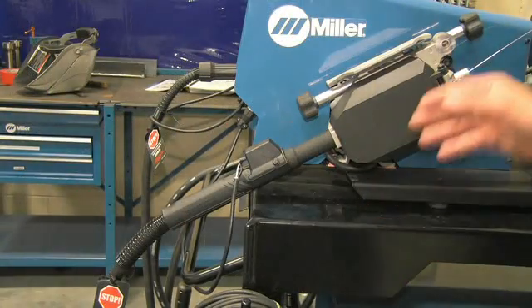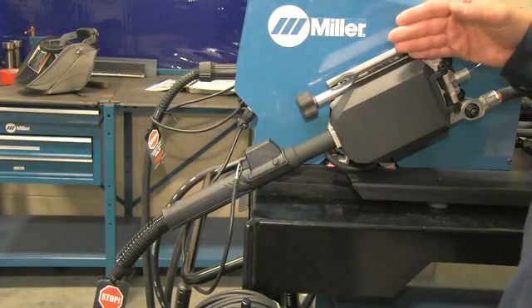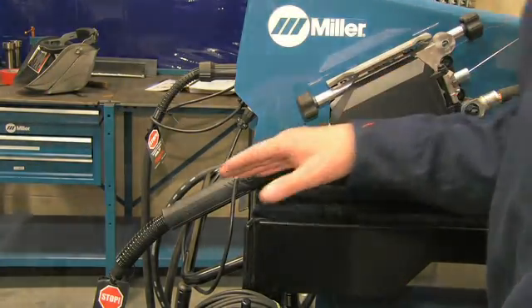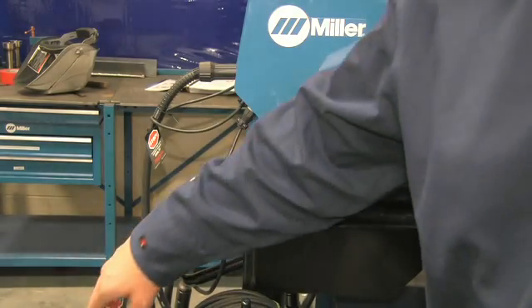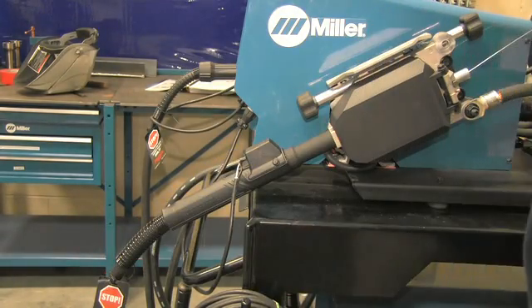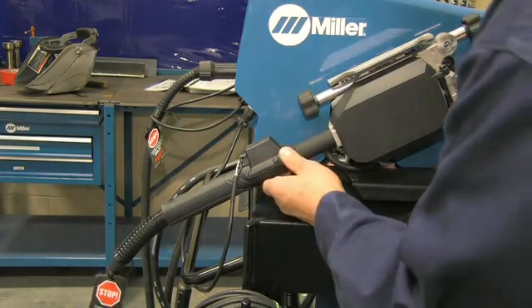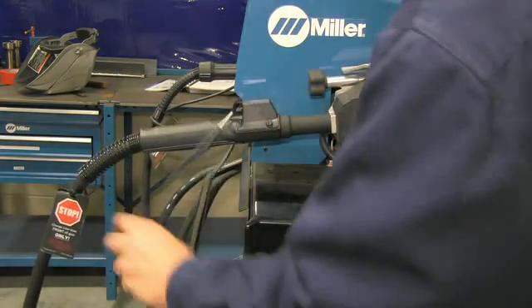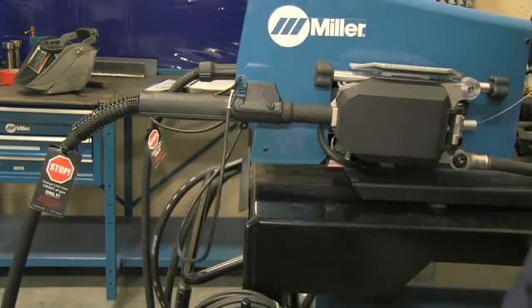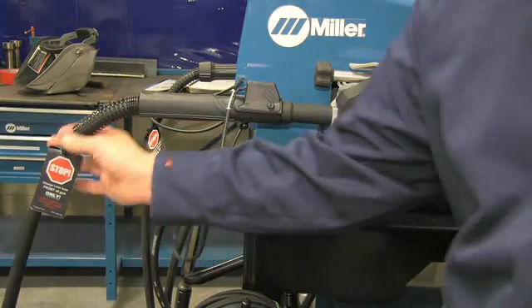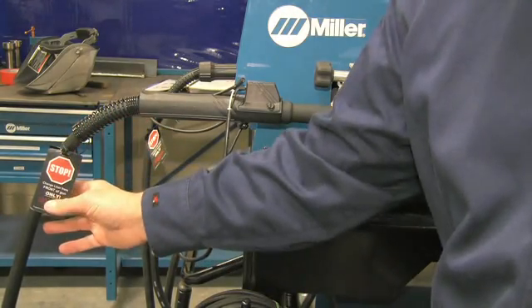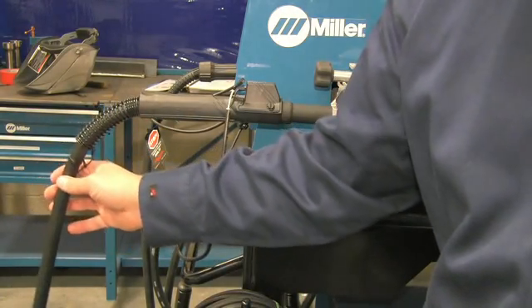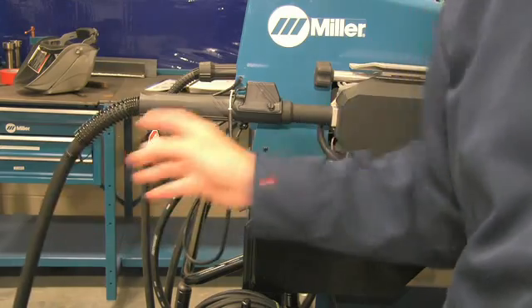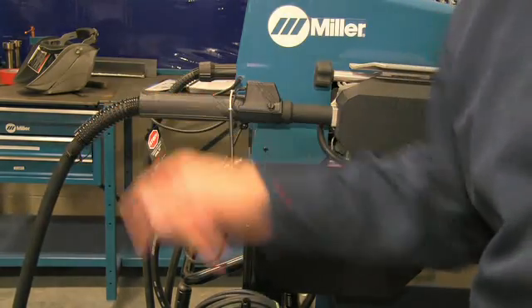So as I mentioned, with the wire drive housing set at 45 degrees, there's a nice gentle slope of the MIG gun as it goes down to the floor going to the weld station. So as you can see, if I loosen that tension knob and bring it up to 180 degrees, you can see this bend that we're going to get in the MIG gun, and over time this is going to get more severe and more severe, and this causes a feeding issue right here in this area over time.